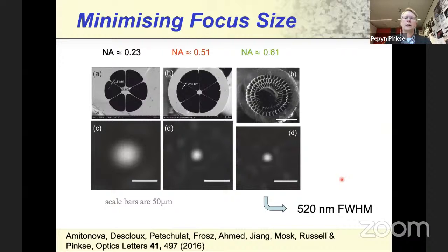A question if you want to do imaging through a fiber like this is how small can you make your focus? What is the resolution of your imaging technique? And a simple formula shows you that the size of the focus is inversely proportional to the NA of the fiber, basically the index contrast of the material of the core and the cladding. Now, there's a limit to how high you can make the index of a fiber. There's also a limit to how low you can make the index of the cladding, and the lowest index that you can make without too much effort is basically 1. Namely, if you surround a fiber by an air cladding.